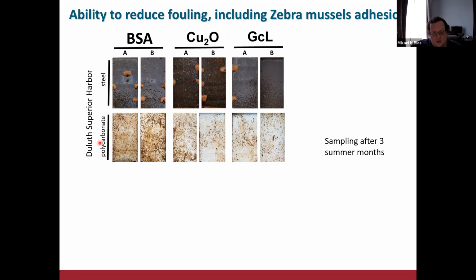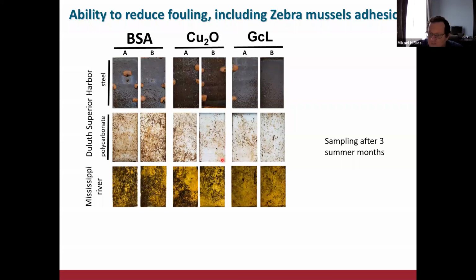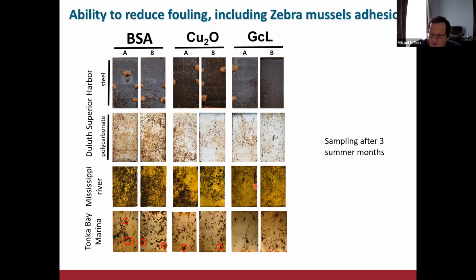Not too surprising. It's not a very heavily fouling area, but you can still see that you have a lot of material on the coating, and as you go towards the enzyme, you have a lot less material on the coupon. Same goes for the Mississippi River sampling. You see the polycarbonate is completely covered with algae, and as you go towards the enzyme, it's less and less covered. And the same goes for experiments in the Tonka Bay Marina, with the difference that here we had a very high number of zebras, and we show that not only is there less algae sticking to our coating with the enzyme as compared to other treatments and control, but there are also no mussels adhering to this surface. So very, very intrigued by this performance.